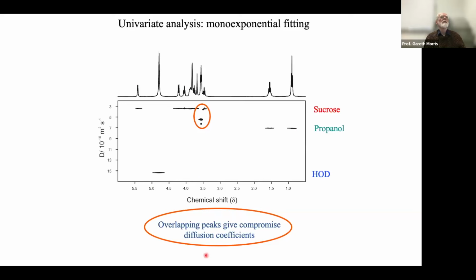Now, if we do a standard mono-exponential fit, what's sometimes called high-resolution DOSY, our basic assumption is that there's one species per peak, and therefore mono-exponential gives us the right diffusion coefficient. Now, we know that this is often wrong, but still we can make allowances for that. And so what we see here is that we get the overlapping peak giving us a diffusion coefficient, which is intermediate between that of propanol and that of sucrose.